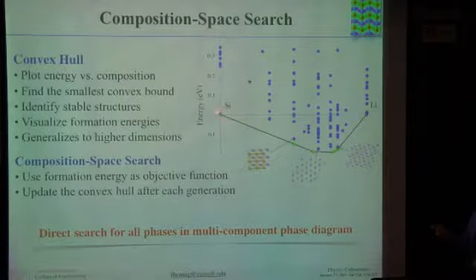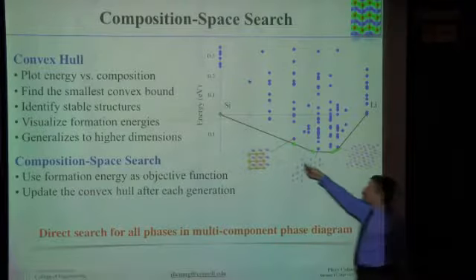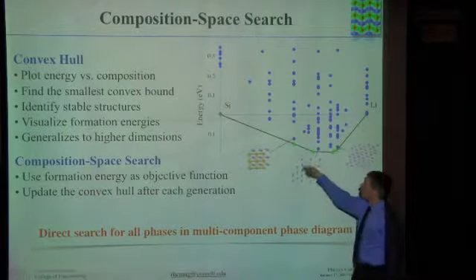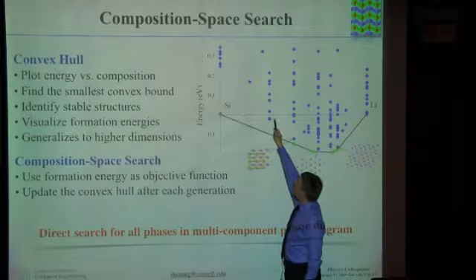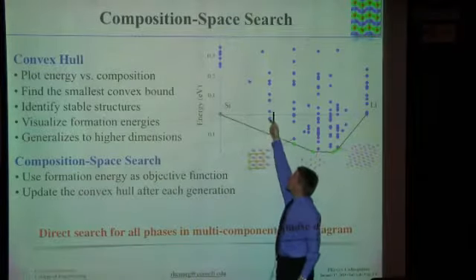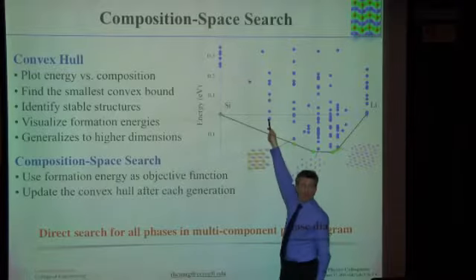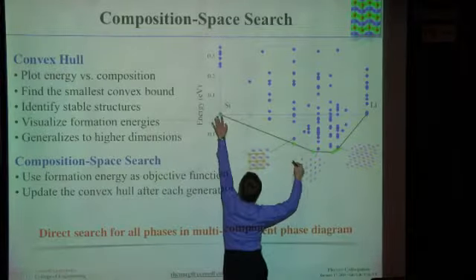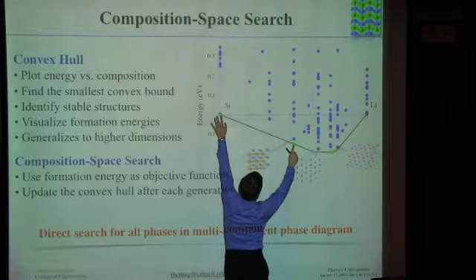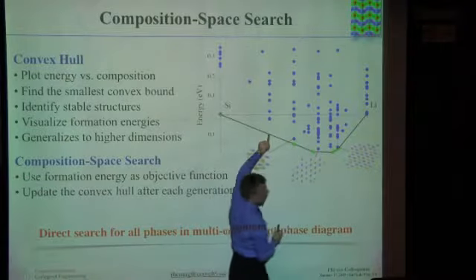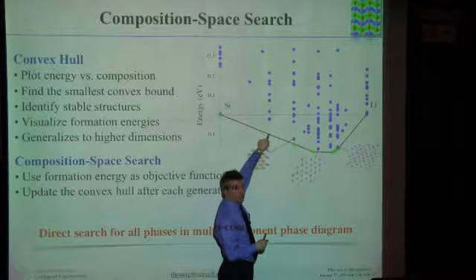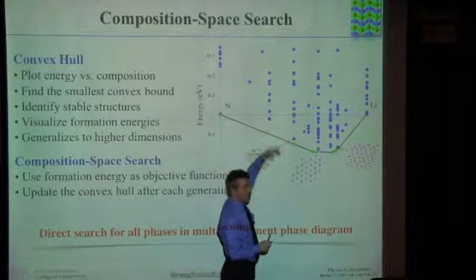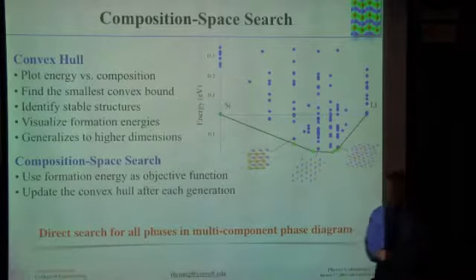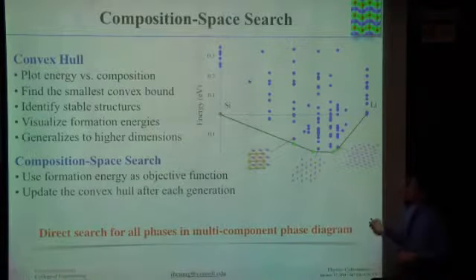So composition space search: what we're doing is a convex hull construction, because a stable structure means it's got to be on the lower part of the convex hull of those points. So if you would, for example, look at this structure, this is the lowest energy structure at that composition, but this material would decompose into a mixture of pure silicon here and this lithium silicon 50-50 compound. And then the energy would correspond to that point down here. So it would be a two-phase mixture. So any point not on the convex hull is a two-phase mixture in a binary system, could be three-phase mixtures in ternary systems. So we use that as our criterion for stability.